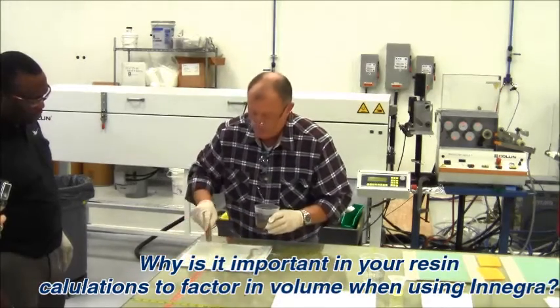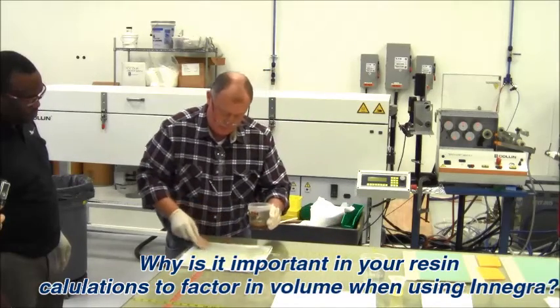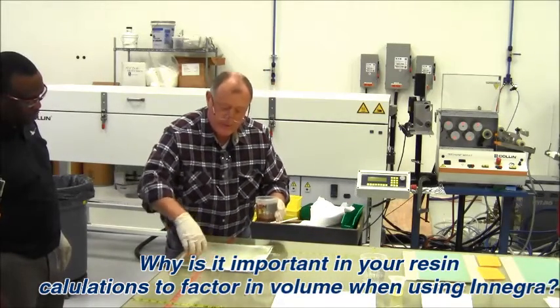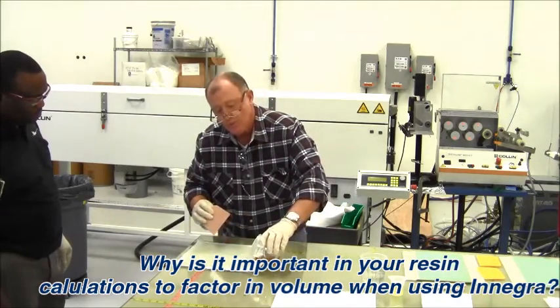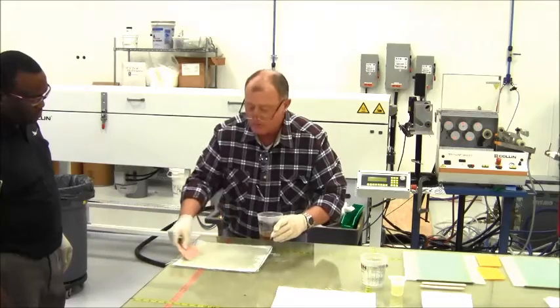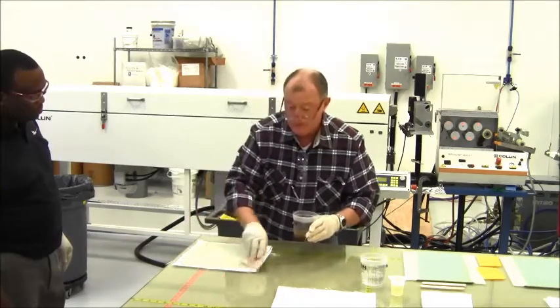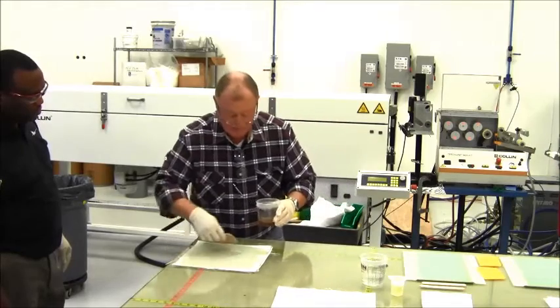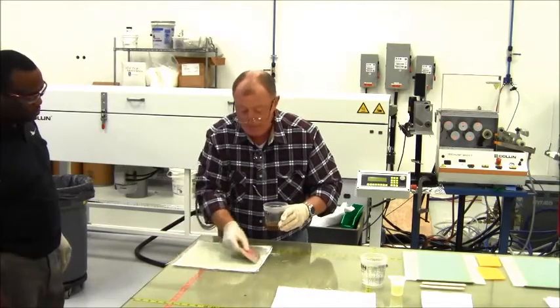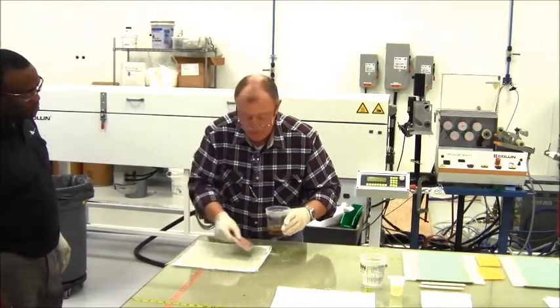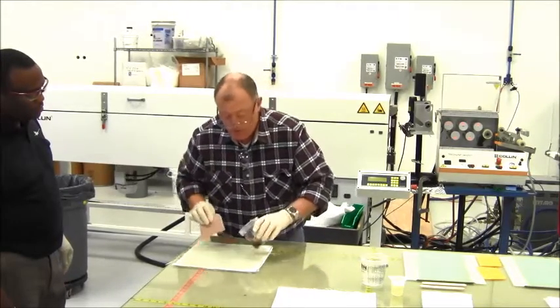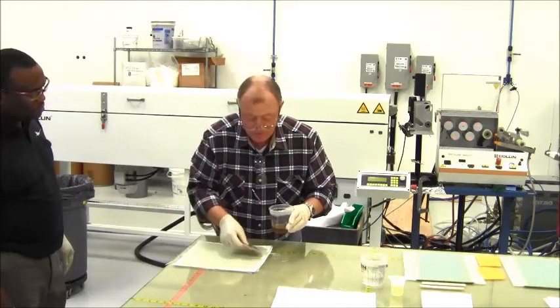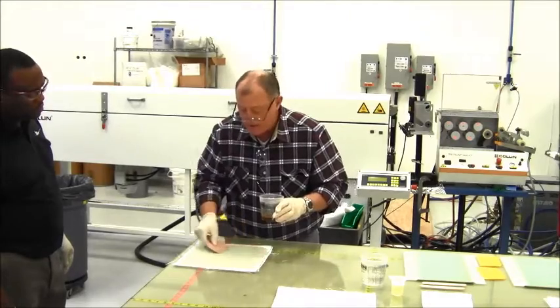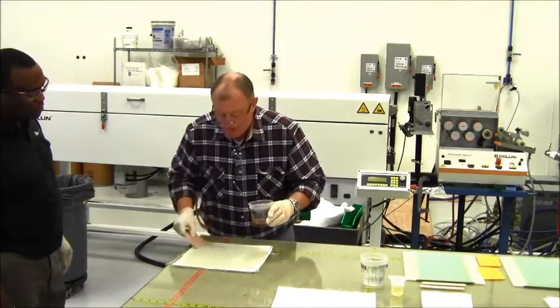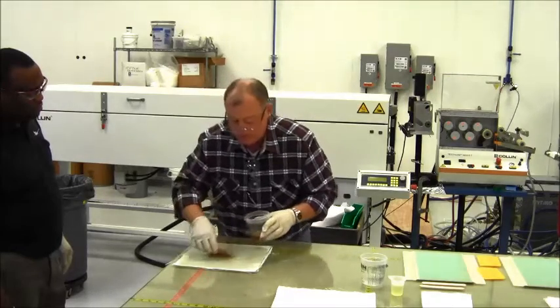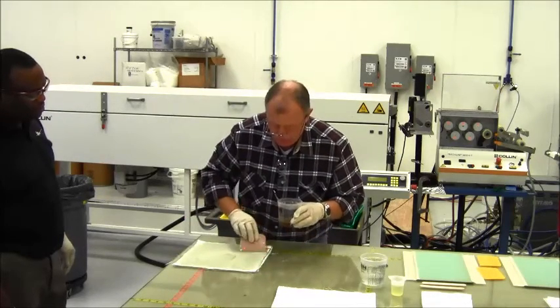And why is it important in your resin calculations to factor in volume when using the Innegra? Because a lot of times, in the old days, when we would do resin calculations for our materials, we would always do weight of the fabric, weight of the resin, to come up with the fiber volume fractions that we were looking for. With Innegra, that's not really possible because it doesn't absorb the resin like glass does. So what we have to do is take into consideration the volume of resin it takes to actually encapsulate the particular fabric style that you put onto your laminate, so that when you mix up your resin, you're not short and you're not over.